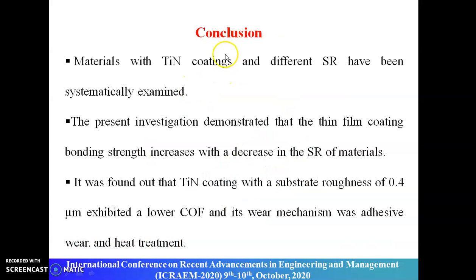In the conclusion part, materials with titanium nitride coating and different surface roughness have been systematically examined. The present investigation demonstrates that the thin film coating's bonding strength increases with a decrease in the surface roughness of materials. It was found that titanium nitride coating with the substrate roughness of 0.4 micrometer exhibited a lower coefficient of friction and wear.